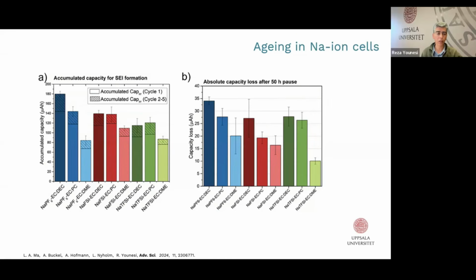But as you see in the dashed line area, there is still some reduction charge consumed to further form SEI in the following cycles. This also highlights that, depending on what electrolyte chemistry we use, the electrolyte reduction and SEI formation may not be fully complete on the first reduction, and may require further reduction in following cycles. One reason could be that part of the SEI formed during the first cycle is dissolved back into the liquid electrolyte solution.